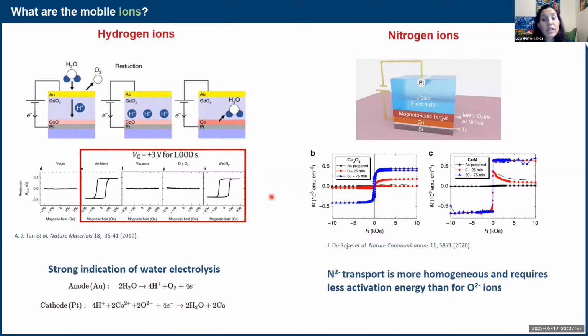So, and with the cobalt nitride, they could do the same. They could see that the nitrogen could be moved back and forth, and that the nitrogen transport was more homogeneous. So it probably has a front that really goes into the layer. This is potentially better for the material, because it might damage the material less if you cycle it a lot. So that is a positive aspect.